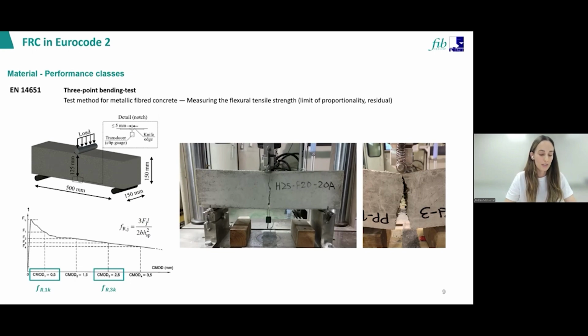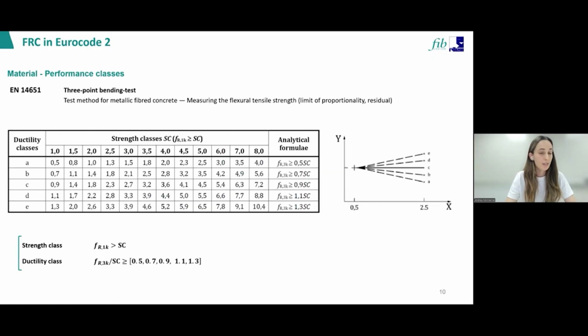So based on this residual strength, what Annex L does is classify the different fiber reinforced concretes according to strength and ductility. The classification proposed in Annex L is based on the characteristic residual strength obtained from the 3-point bending test, particularly the characteristic values FR1 and FR3. The strength class is defined according to the characteristic value FR1, while the ductility class depends on the ratio between the characteristic value FR3 and the corresponding strength class. As shown in the figure, this classification allows distinguishing between materials exhibiting softening behavior and materials showing hardening behavior